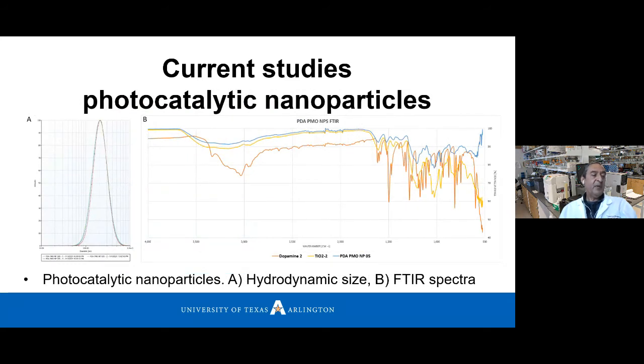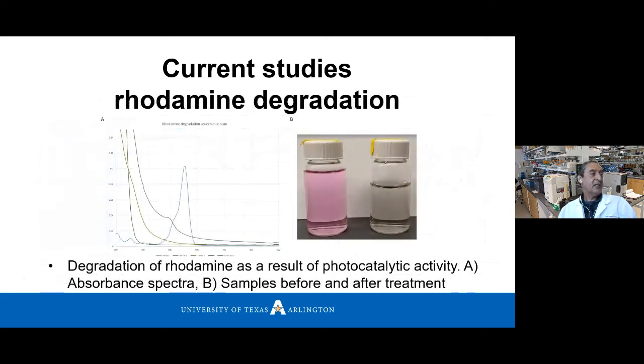Then we began preparing our photocatalytic nanoparticles. To your left, you see image A. That's the sizing of this nanoparticle. The size is around 200 nanometers. And to the right, you see the spectral image that confirms the formation of the coating on top of the titanium oxide core. Can you please move to the next one?